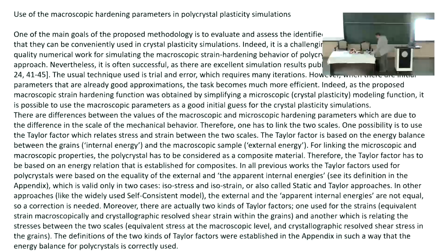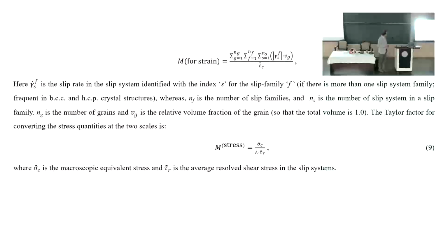So, to go from the microscopic to the macroscopic level, we will use the Taylor factor. In a simple procedure, we can transform our fitted macroscopic parameters into microscopic polycrystal plasticity parameters. The Taylor factor is a ratio between the macroscopic strain rate and the local shear strain rates.